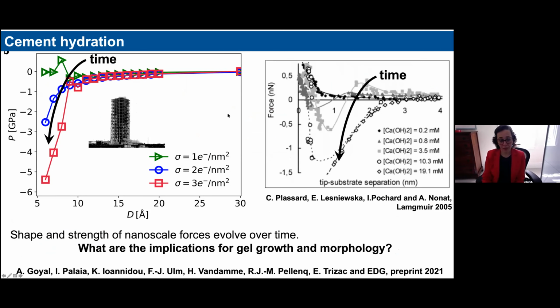And so now you end up with a different pressure profile between the two surfaces as you increase the charge over time. As I said, you can understand that interactions can combine short-range attraction and repulsion in the very beginning, and then the attractive part becomes more and more prominent due to the phenomenon that I was telling you about. And this type of profile, and the change of the profiles over time, closely resembles the first measurements that were made nearly 20 years ago by the group in Dijon, where they had an AFM tip on which they grew CSH, and they used it to poke on CSH produced during hydration of a cement grain surface, in a very nice set of pioneering experiments.